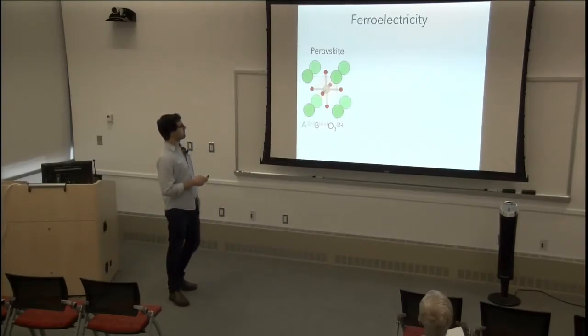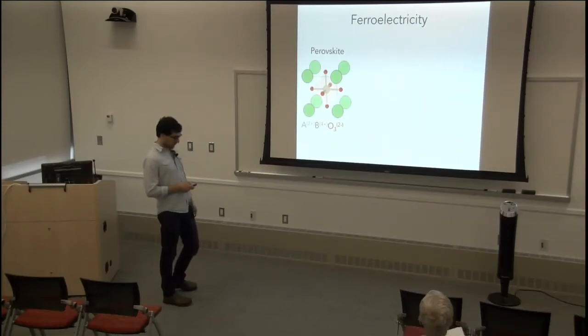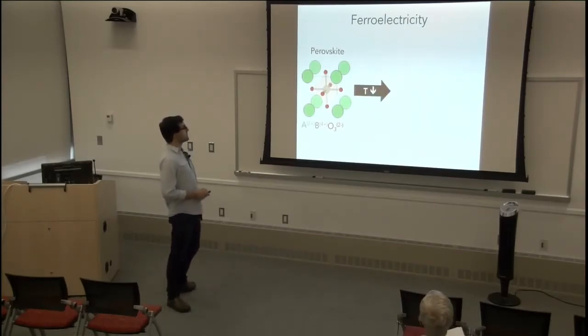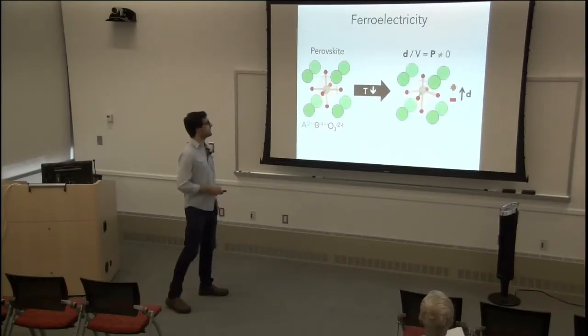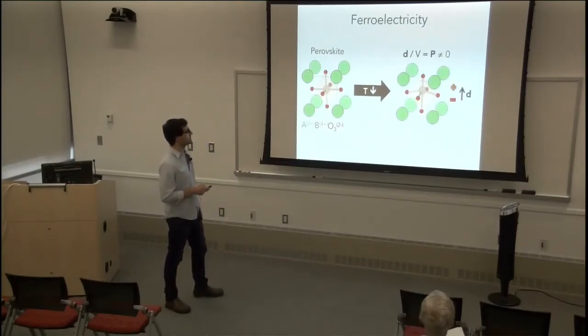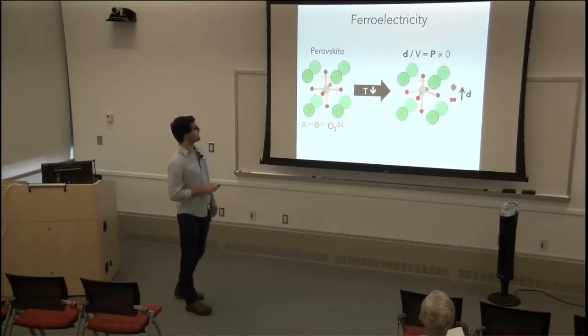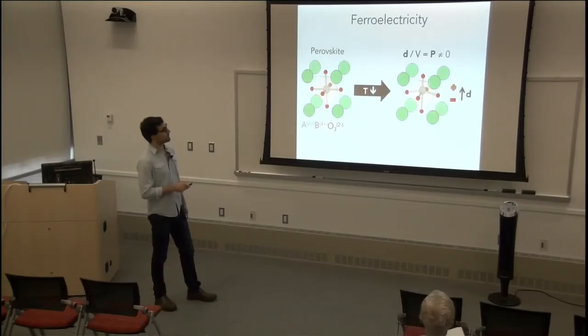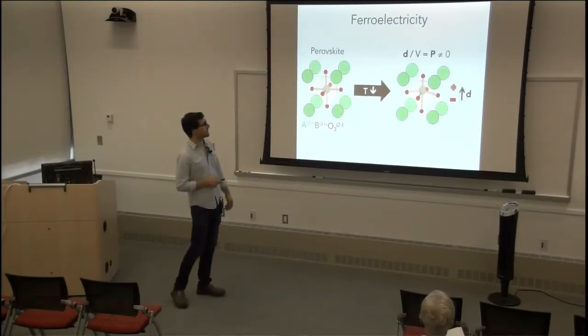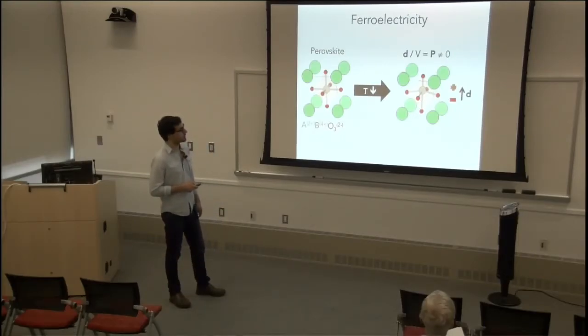But what happens if we take this system and we start lowering the temperature? What happens is that this system spontaneously has a transformation, and the B cation moves up. What this means is that now you have a plane of these B cations, which gives you a positive charge, and you have this plane of oxygen anions, which give you a negative charge. So you have these positive and negative planes, which create a dipole moment, and a dipole moment, if you divide it by the volume, gives you the polarization, which is something non-zero.